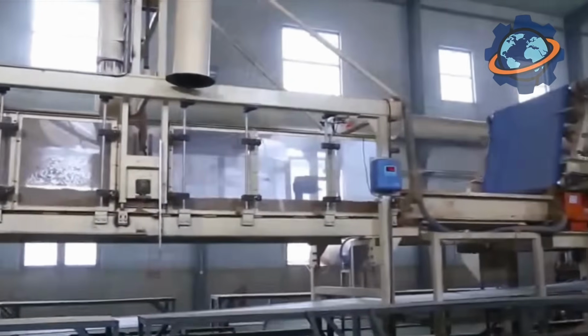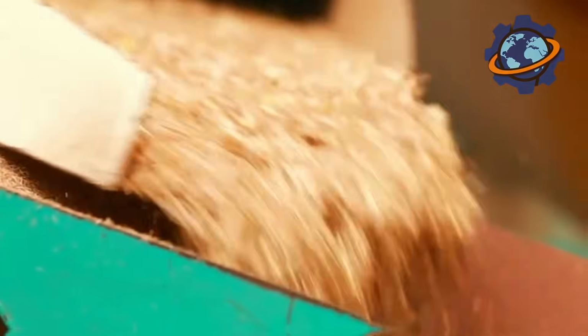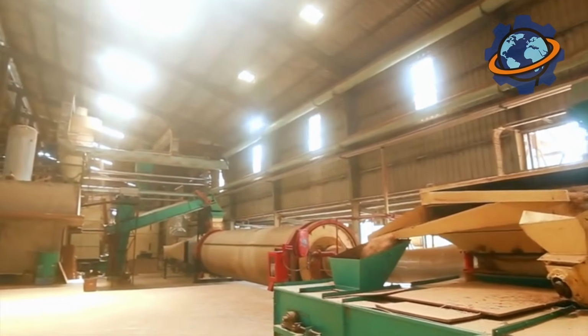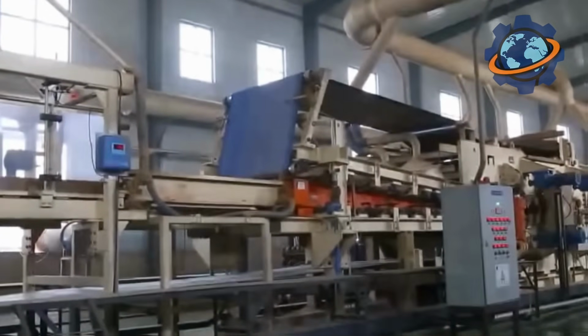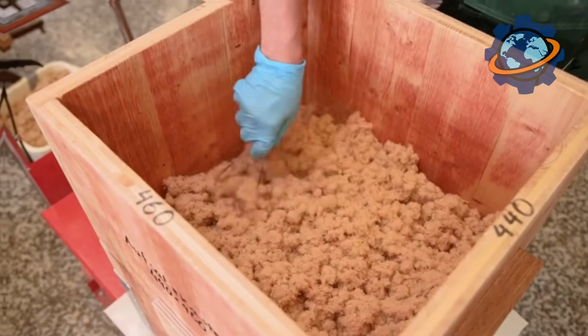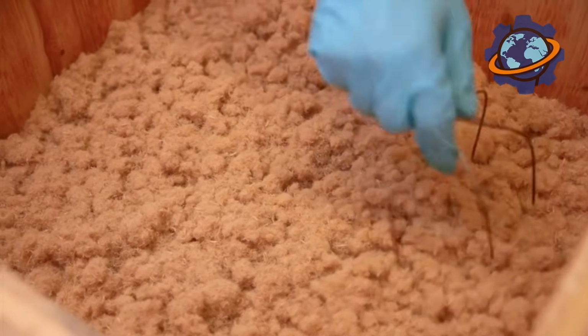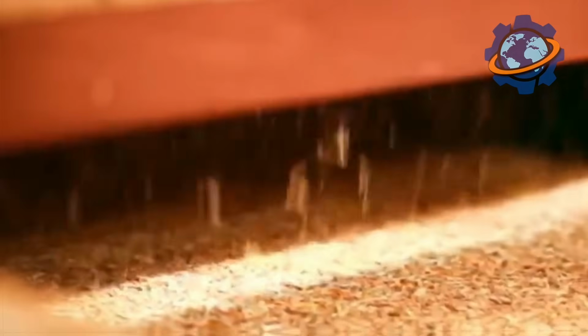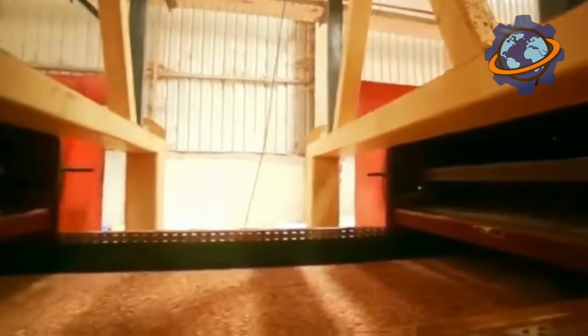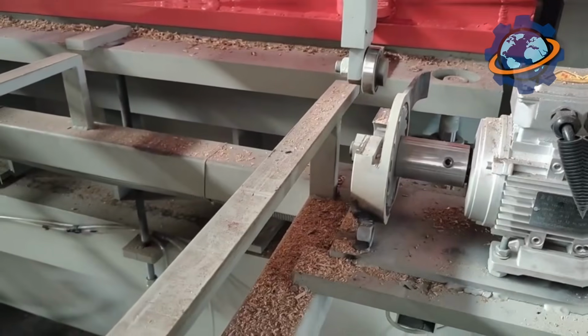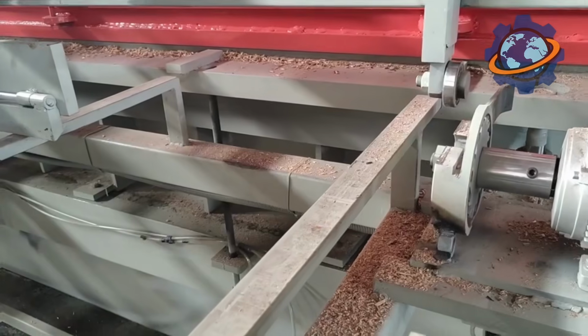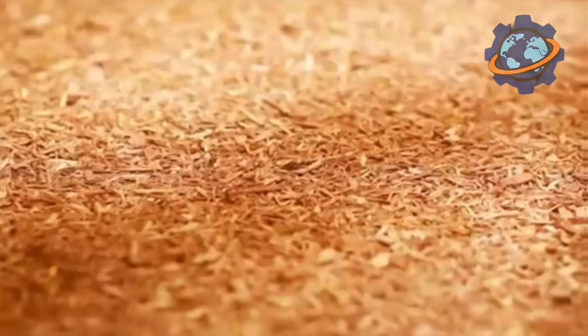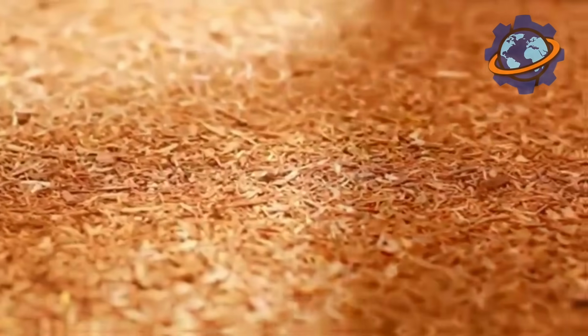First, it creates a perfectly even bottom layer, using the smallest fraction of chips. Immediately after this, a much thicker middle layer, consisting of large and strong chips, is laid on this base. Finally, the entire mat is covered with another layer of the fine fraction, creating a mirror image of the bottom layer. This carefully designed structure, resembling a sandwich, provides the unique properties of the future board. Its smooth and dense outer layers are ideal for further sanding and laminating, while the strong inner layer gives the board the necessary rigidity and the ability to securely hold fasteners.